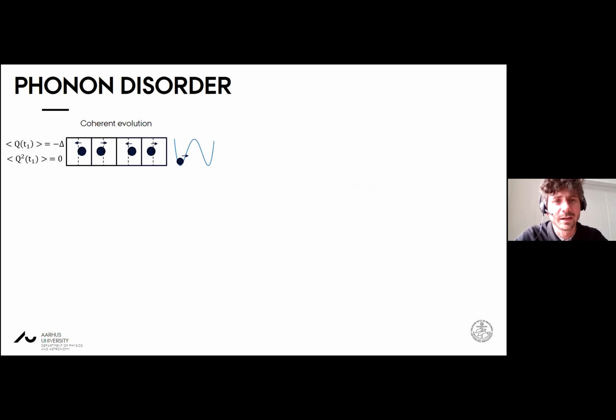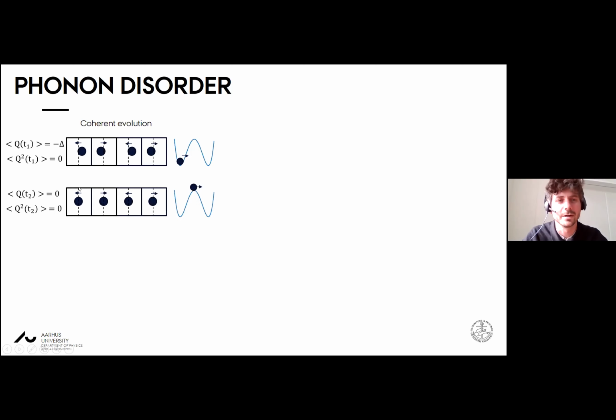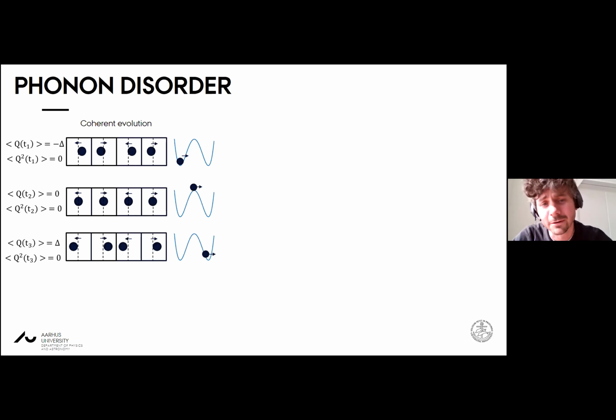Okay, and my final thing before I tell you how we're going to measure this is the implications of a coherent transition and a disordered transition on the evolution of the system. We heard about, I think in both talks, Andrea mentioned pushing the system over the barrier into a new state. And if we have a coherent evolution, that's quite straightforward to imagine. We start in a system with a dimerized state, we initiate some pulse, some force, which causes the dimers to break. They move along the potential energy surface and they get to the state where there's no net distortion in the system, but they might still have some momentum in them, which would allow the system to go over the barrier into the other potential.